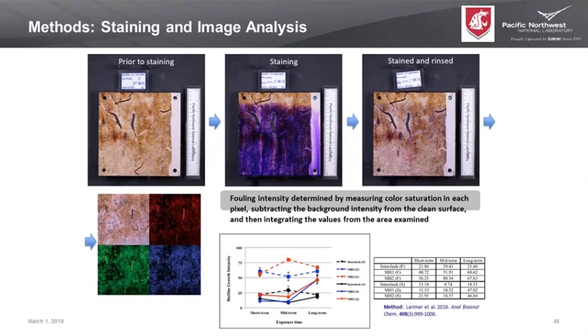So some of the quantitative methods. For looking at microfouling, one of the things that we developed at PNNL is a photographic and visual-based method where we take a coupon, apply a set of stains. Those stains help reveal the organisms, but they introduce colors such that when we take a digital photograph, we can separate the color channels, and then with a software script that we've written, measure pixel by pixel exactly how much fouling has accumulated on the surface.